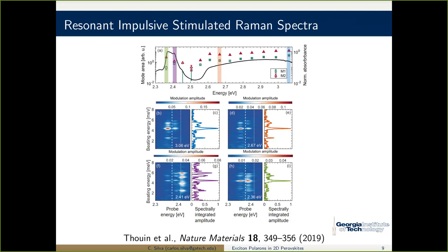I'm not only concerned about the relaxation of the excited carriers, but about the population. The number of carriers depends on what the cross section is for the absorption at that wavelength and how much juice I used in my laser. What was the fluence of my pulse? Those two things will determine what the actual density is. I can tell you, we can vary this. At Georgia Tech here, we have a 100 kilohertz laser, which means that our pulse energies are low. And so our fluences, the joules per centimeter squared, can go from very, very low, fractions of a nanojoule per centimeter squared, to microjoules per centimeter squared. These are done in some intermediate regime because, of course, in the part that I'm about to get to, we're also trying to look at many-body exciton effects and the consequences of exciton polarons on those.